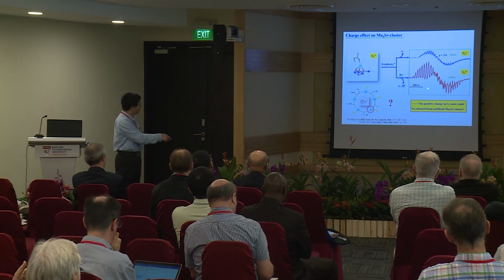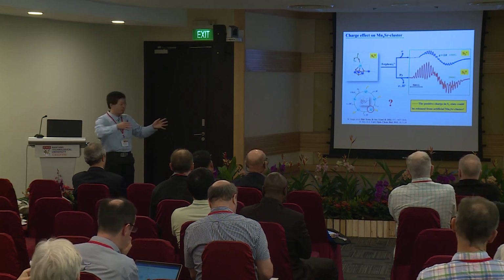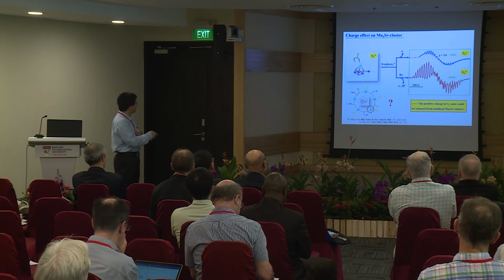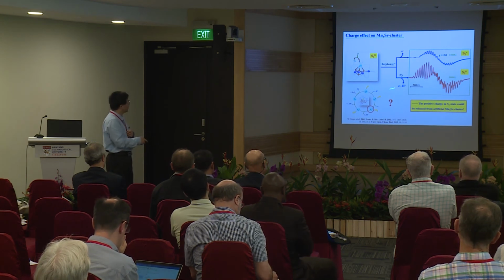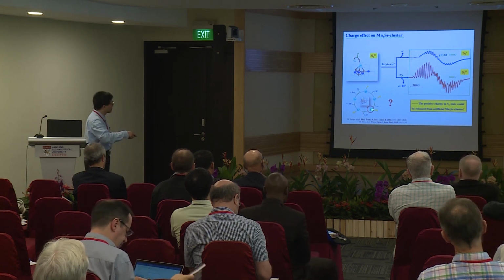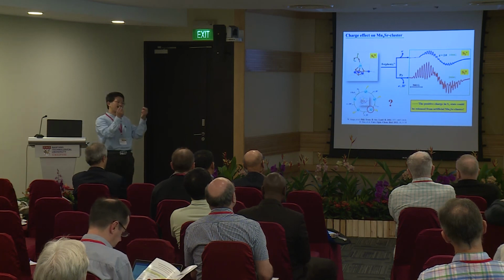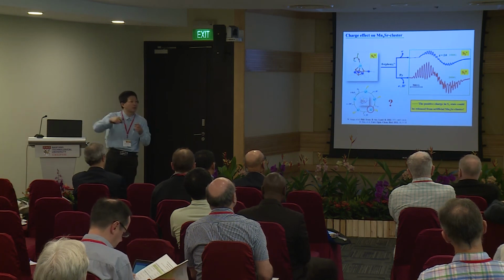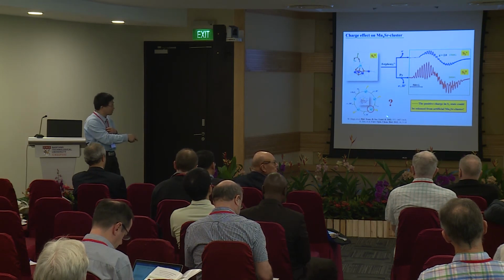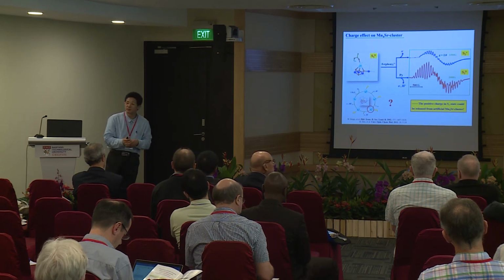We can see, obviously, the amplitude increase, and the signal becomes much broader. What does that mean? It looks like the charge has a significant structural effect on this cluster. And for PSII, in the cycle from S1 to S2 state, people say only one electron can be released, but it's possible to get a proton release. Our model suggests it may still be possible.